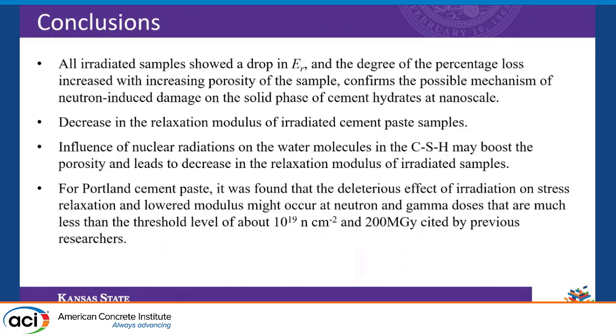To conclude, we saw a large drop in the reduced modulus, which may be due to increase in the porosity of the sample, confirming the possible mechanism of neutron-induced damage. We also see a decrease in the relaxation modulus of the irradiated cement-based samples, which may be due to the effect on water molecules in the CSH leading to increased porosity and change in microstructure. These deleterious effects of irradiation on the relaxation modulus and elastic modulus were found at much lower threshold levels compared to reference levels reported by previous researchers.